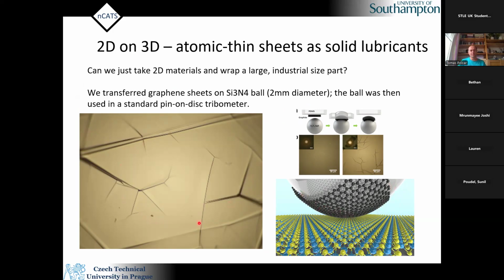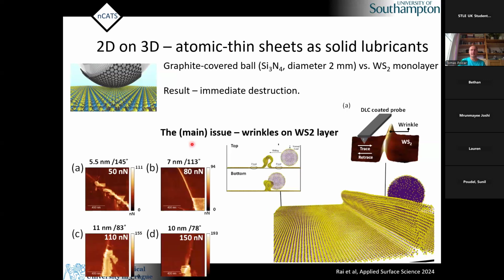But the problem is, if you cover the ball, you see that you have these wrinkles, because you try to cover a 3D object, which is a ball, with a 2D material. So it cannot really fit very well. You have some wrinkles, some problems here. And because of that, we realized that it will not work, because these wrinkles are very easily broken. We just destroy them. There was no way to convince this system to reduce friction to 0, because we almost immediately destroyed one or another 2D material. But again, the story is not about trying and failing. The story is to get the maximum from the failure.